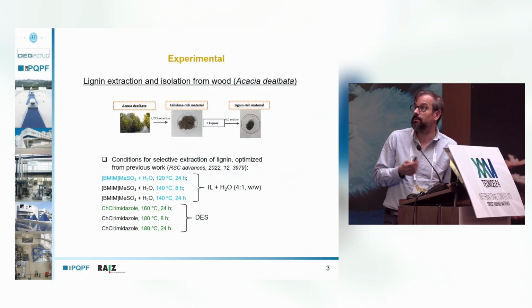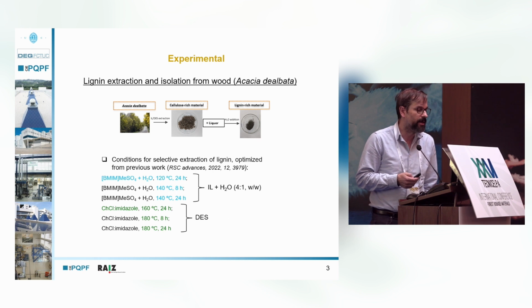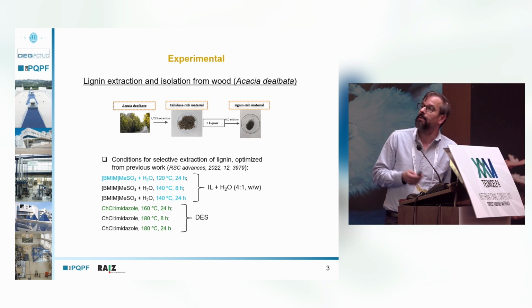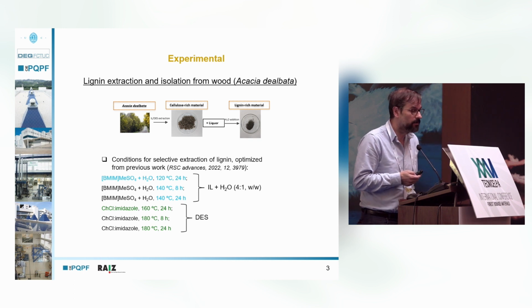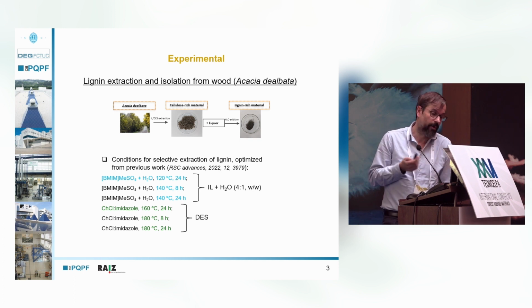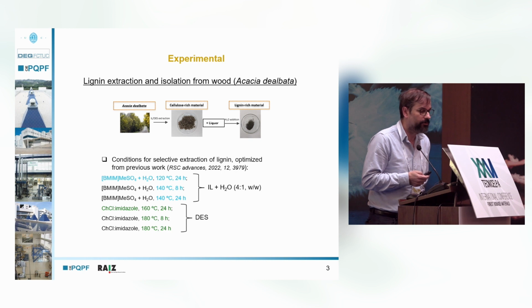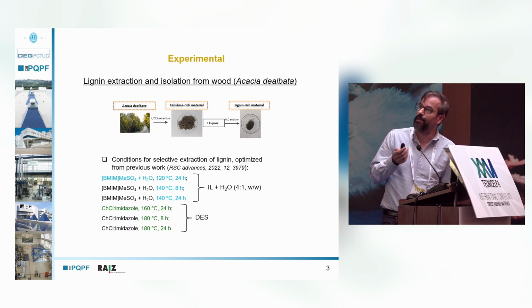The experimental part comprised two sections. The first was the lignin extraction and isolation from wood. The lignin extraction and isolation had two main steps. First, it was the extraction using ionic liquid or deep eutectic solvent of the lignin from wood, which enabled a first fraction, a cellulose-rich material, and a dissolved fraction, which contained lignin. From the dissolved fraction, after adding water, we could easily precipitate the lignin-rich material.